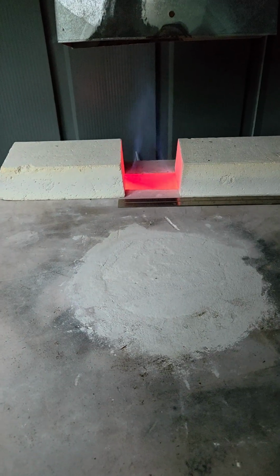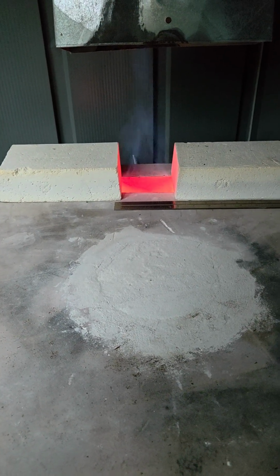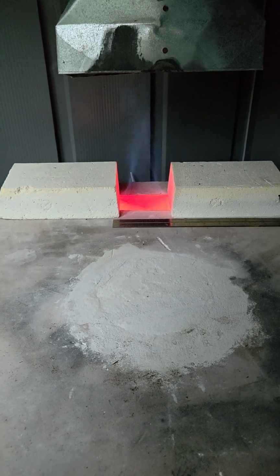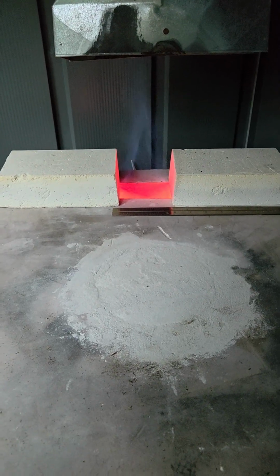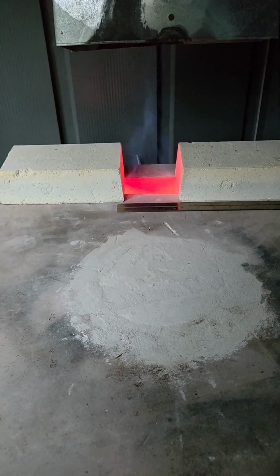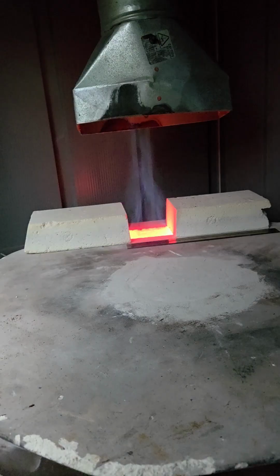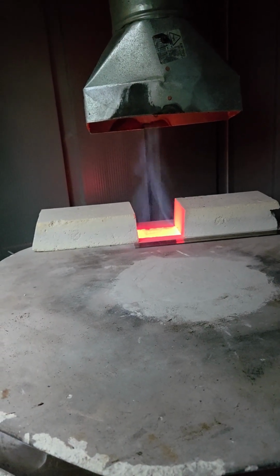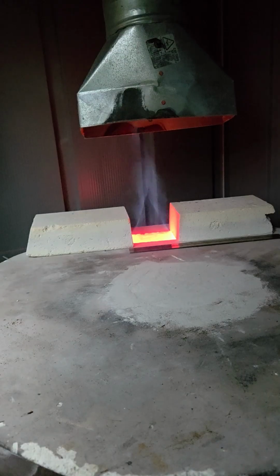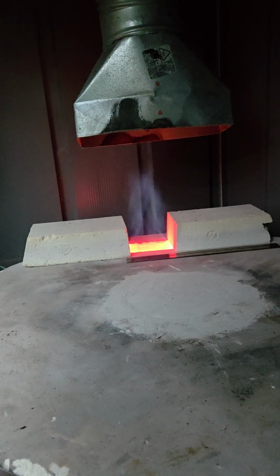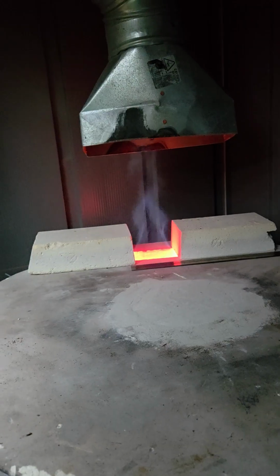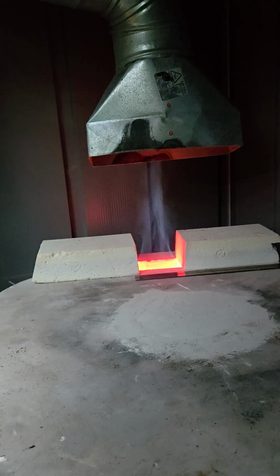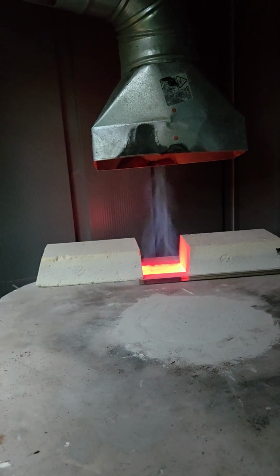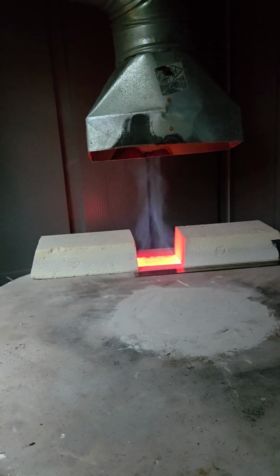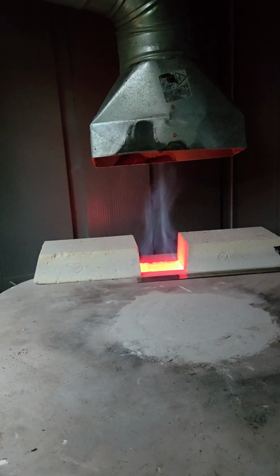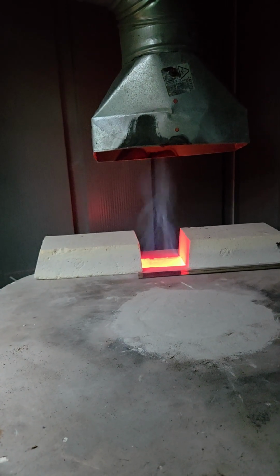So now it's been open to 3.5 inches, and the pressure set to 2.1 psi, and now we're going to do the climb up to the final part. It's been about half an hour and the temperature's up to about 1,020 degrees centigrade. This is what the reduction flame looks like with a cell phone camera. In real life, it's not quite as intense, and right now I've got what I would call medium to medium strong reduction, as the glazes I've got in there like a strong reduction flame.